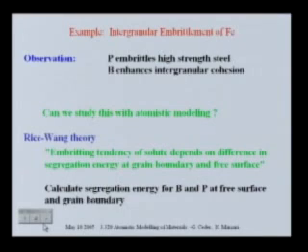And this is one of these things that you really think you need a multi-scale, big kind of modeling approach on. Essentially, the observation is that there are quite a few impurities in steel that embrittle steel, and there are some that actually enhance the intergranular cohesion. Typical examples are phosphorus, which is a really bad embrittler of high-strength steel, whereas boron tends to enhance intergranular cohesion.